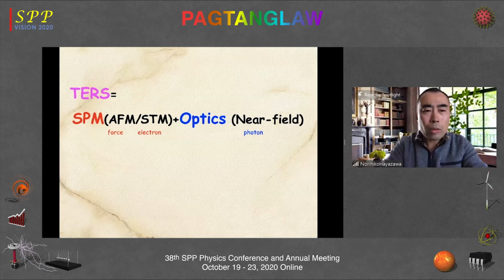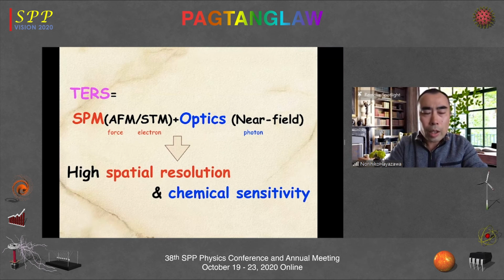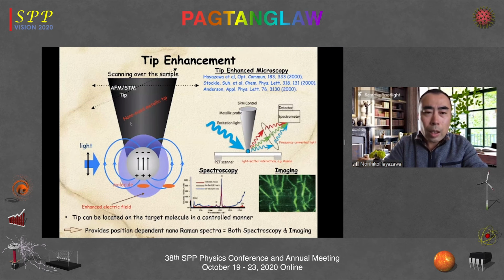Anyway, the topic I'm going to talk about is tip-enhanced Raman spectroscopy, TERS. This is a combination between scanning probe microscope and optics, particularly near-field spectroscopy, so that we can achieve both high spatial resolution and high chemical sensitivity. And very briefly about the tip enhancement effect. When a nano-sized metallic tip is irradiated by the light field, the collective oscillation of the electrons is induced inside the metal. As a result, the enhanced electric field is generated and localized at the tip apex. So when you employ this enhanced electric field as a nanoscale light source for spectroscopy techniques, such as Raman spectroscopy, you can acquire a local Raman spectrum underneath the tip. And also when you scan the tip over the sample, you can acquire local Raman imaging beyond the diffraction limit of the light.